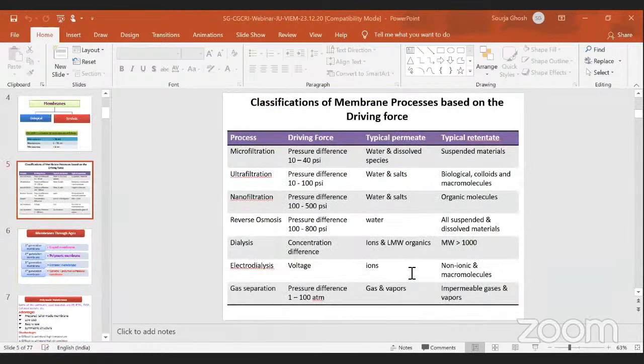Now, the classification of membrane processes based on the driving forces. You know that microfiltration is a pressure-driven membrane process, and the operating pressure is generally low, that is 10 to 40 psi, whereas ultrafiltration is a bit higher pressure, 10 to 100 psi, where it separates biological colloids and macromolecules, and it covers a wide range of separation. Then comes nanofiltration, which requires around 100 to 500 psi, and the pore size of such membranes is less than 2 nanometers. We use this for separation of dissolved contaminants and organic molecules. Reverse osmosis, you all well know, is a high pressure membrane process. The required pressure is 100 to 800 psi, wherein all suspended and dissolved materials are retained by the membrane. We use it for salt separation from the stream.